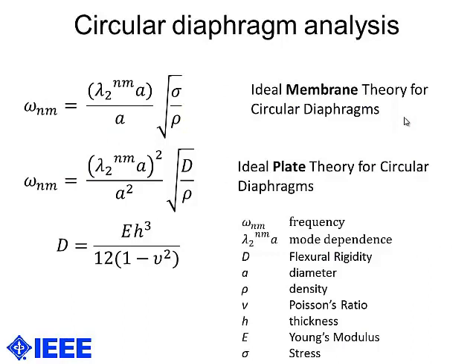To analyze the results, we looked at the membrane versus the ideal circular diaphragms. This is the membrane equation. It has a mode dependence, a diameter, a stress, and a density. The important thing to note in the membrane equation is that it does not depend on the Young's modulus, only on the stress of the membrane.